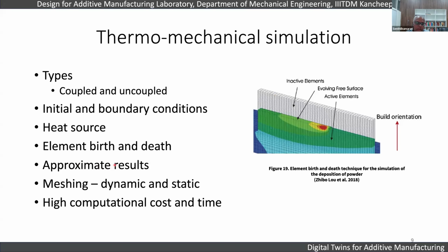And sometimes you can use a dynamic mesh where you can change the size of the mesh, where the interaction between the laser and the material is happening. And in other regions where not much interaction between the heat source and the material is happening, you can use a coarse mesh and a fine mesh. That is what we call a static mesh. Static mesh means uniform meshes all through, whether it is fine or coarse. But in dynamic, you change from coarse to fine as the laser moves in. So that's called a dynamic mesh.